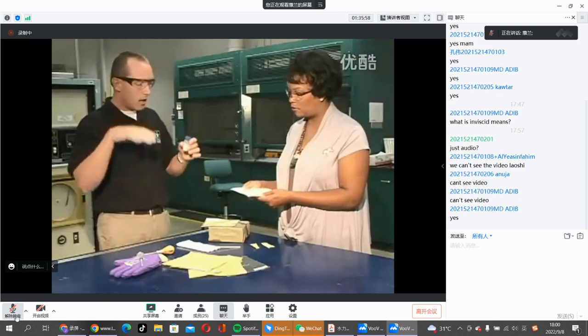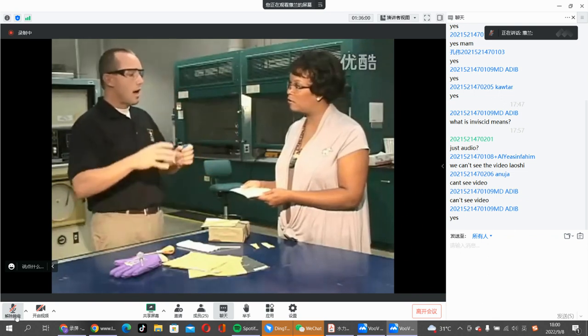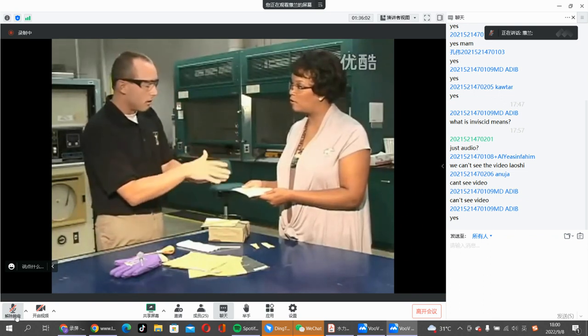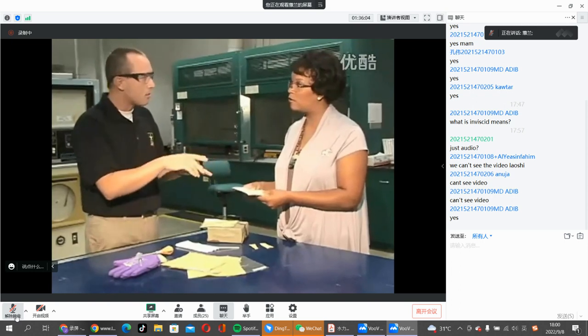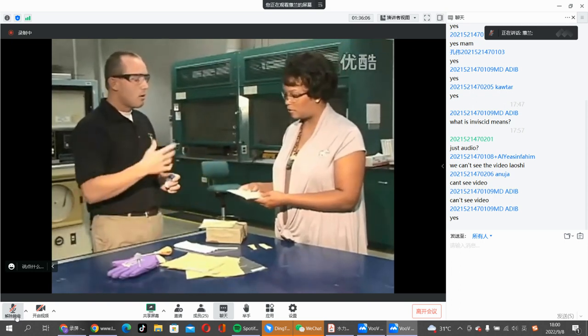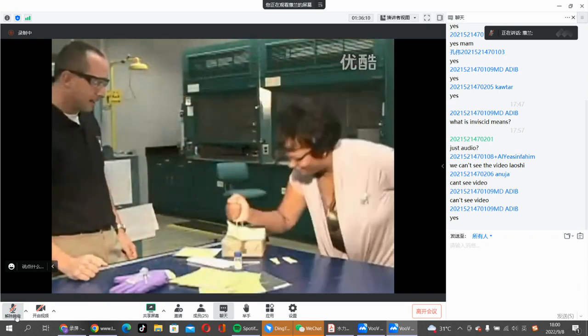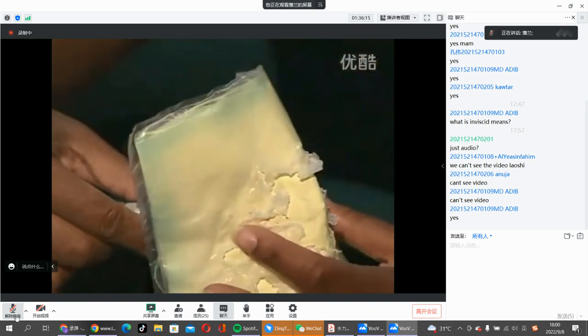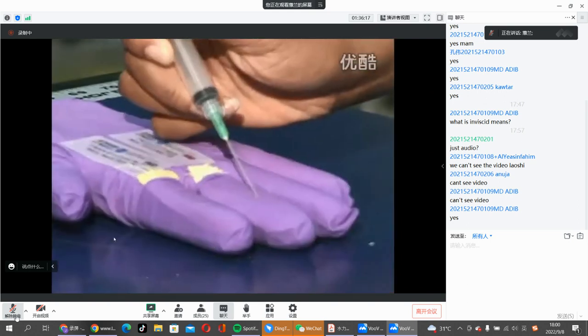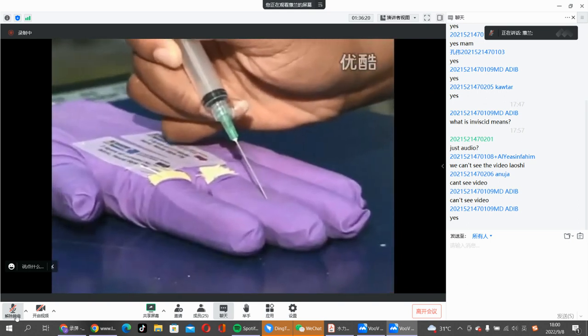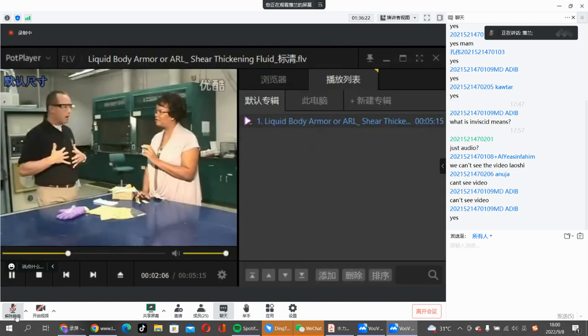We'll dip the fabric in the solution, pull it out again, and then this stuff kind of soaks into all the little nooks and crannies between the fibers, between the yarns and the fabric. Pull off the ethanol, and this gets left behind. But what is different about it is its response to threats, things like puncturing threats. This same technology can be applied to gloves, police, and medical personnel when walking around, but then if a projectile would come in, it would hit.